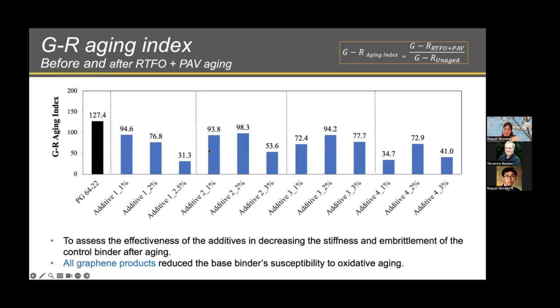blends of binder with additive for cracking or for aging, or the aging rate of these additives, are lower than the base binder. So overall, what we can see here by these results is that the 4 evaluated additives at the 3 dosages for each one apparently reduce the binder susceptibility to aging.